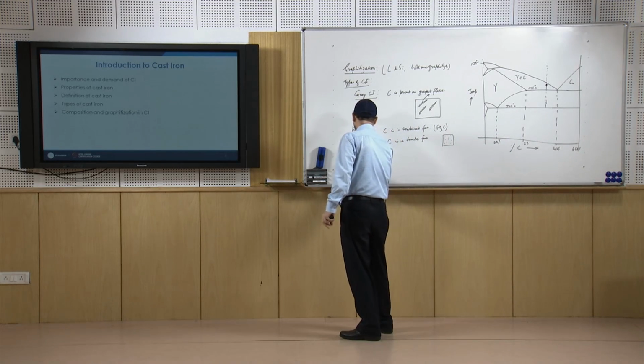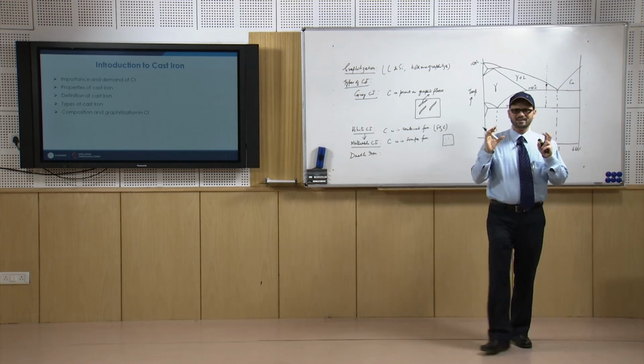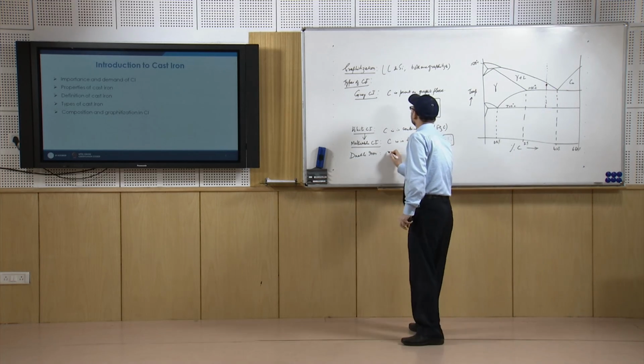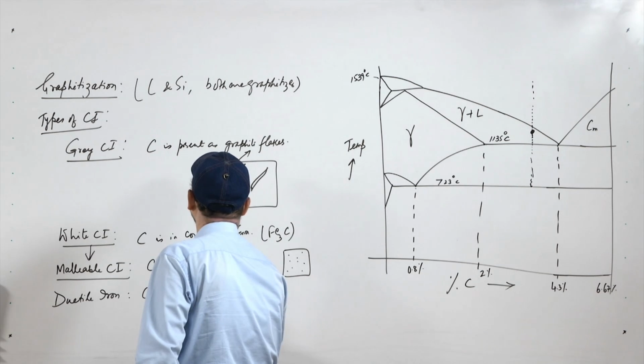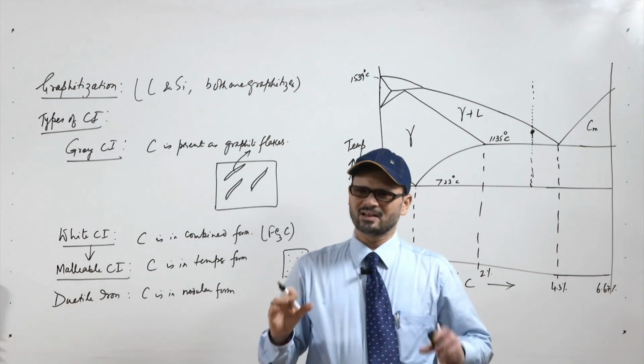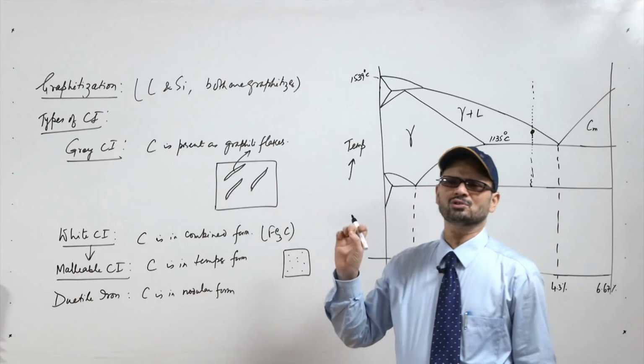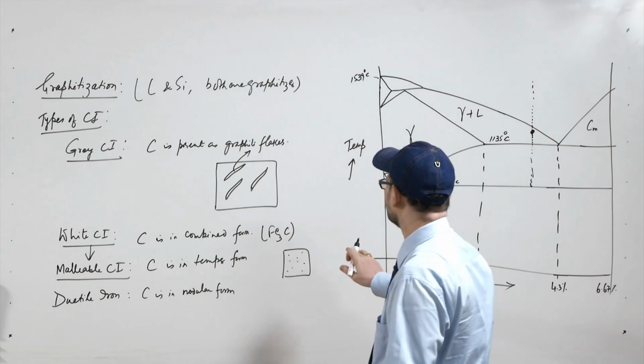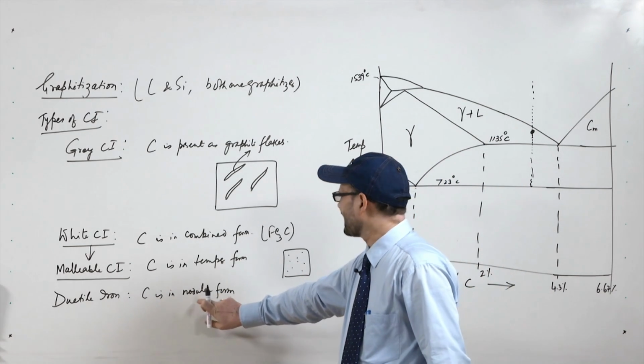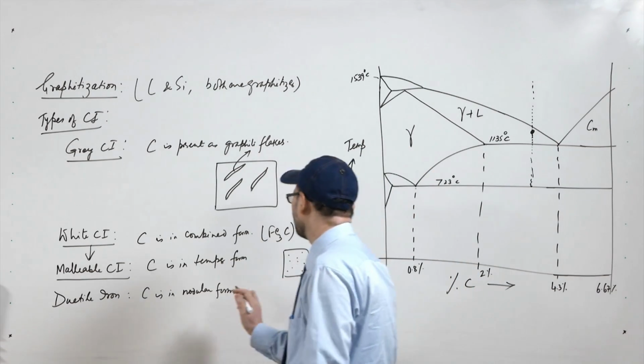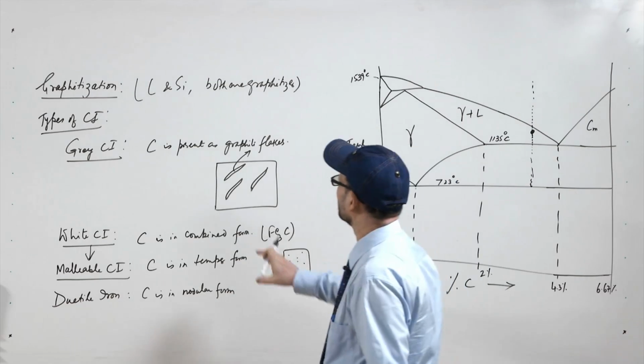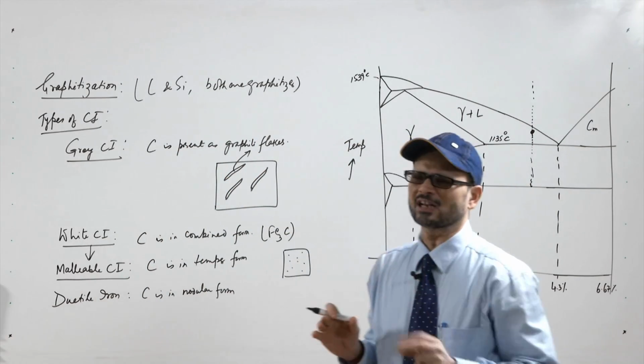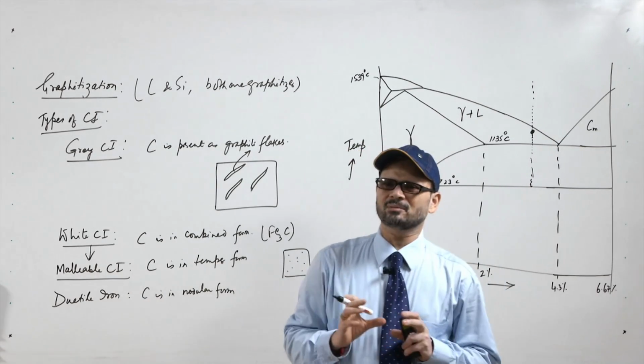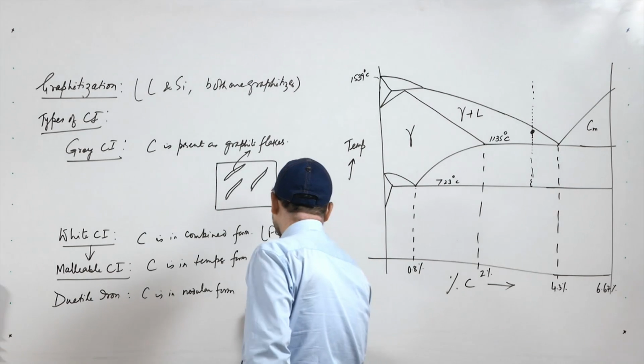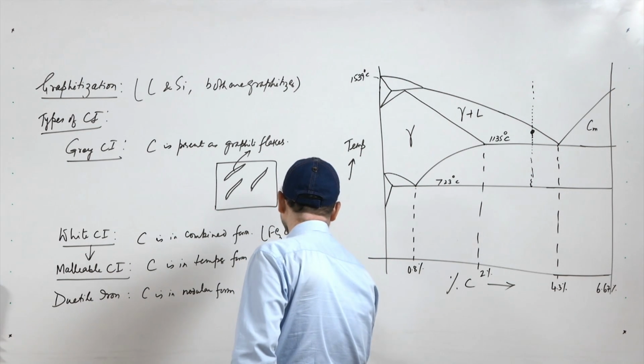The next variety is ductile iron. So, ductile iron is that variety of cast iron where carbon is in nodular form. In this case you get small nodules of free carbon, but in the as-cast form we can get the nodules of graphite by doing a treatment of this cast iron. So, for the same composition of cast iron towards the higher side of carbon and silicon, if we treat the melt with magnesium or cerium or yttrium, then you get a cast iron which has nodules of rounded shape.